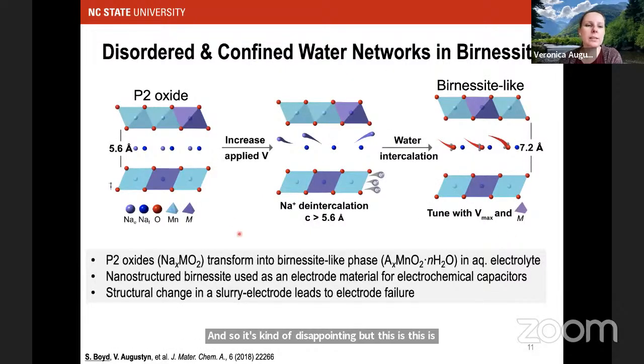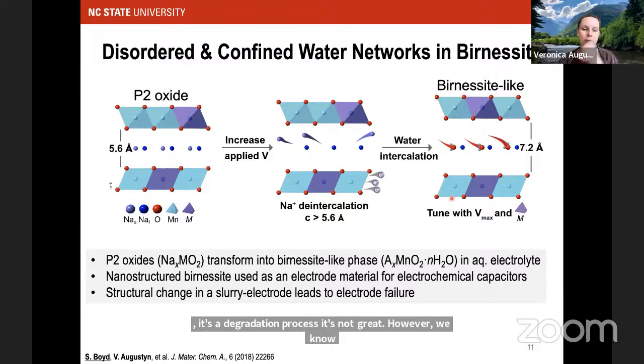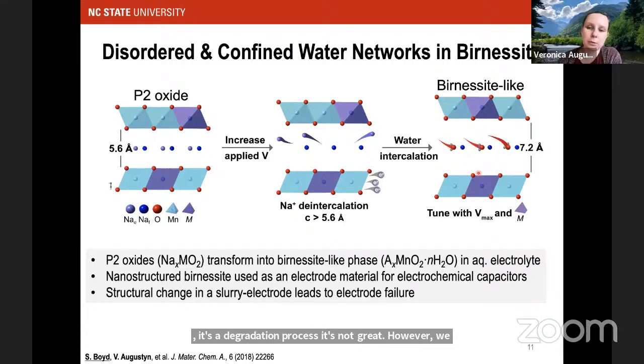So to summarize, if we take these P2 oxides, you apply a high enough potential at some critical amount of sodium deinsertion, water comes into the interlayer to offset presumably the negative charges between the oxygens, and you end up with this hydrated layered material. And if this happens on a slurry electrode, it's a failure, it's a degradation process, it's not great. However, we know that nanostructured birnessite, which has a very similar motif of edge-sharing MnO6 octahedra with water and cations in the interlayer, is used as an electrode material for electrochemical capacitors.